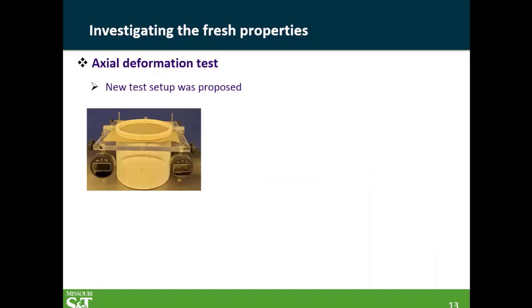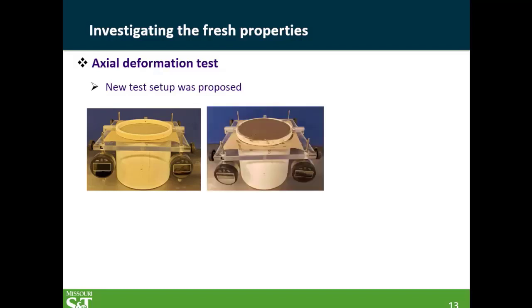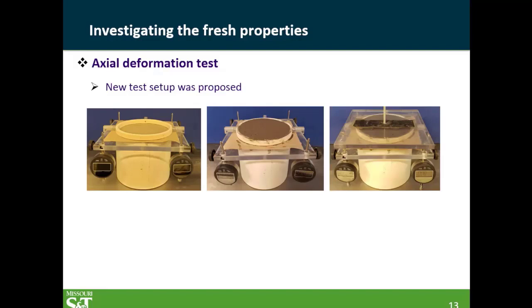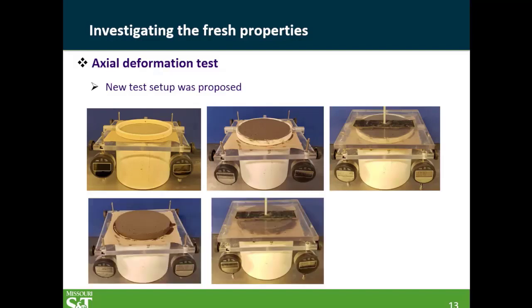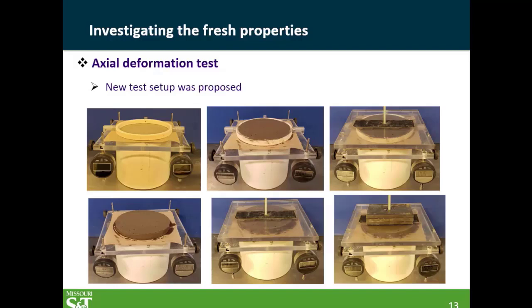For the buildability, we don't have again a standard test. So what we propose over here, we have this plastic ring over there, and we add the concrete under investigation here, and then we start to add different steel masses on top of it. We add different steel plates. The weight of every steel plate is equivalent to the weight of the cement layer over there. So every one of those steel plates represents another layer added on top of the mortar. And then we measure the strain. We have 4 dial gauges to measure the strain, and then we take the average as the strain for